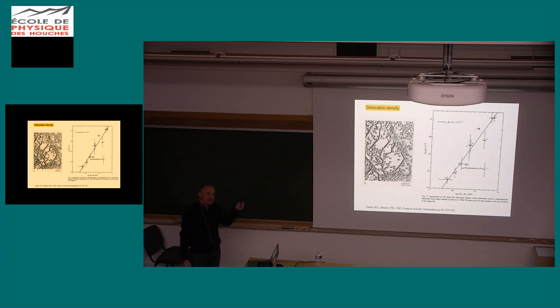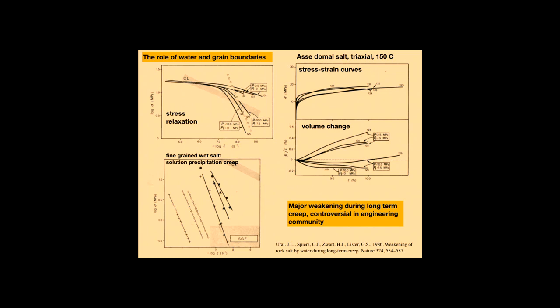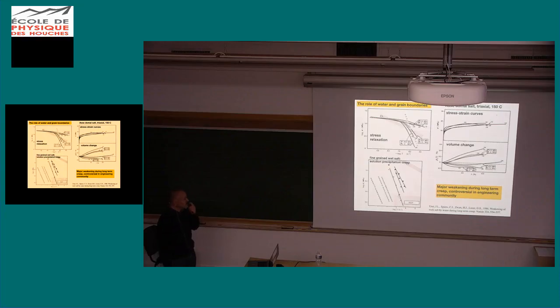So the point I'm trying to make here is that this was fantastic work, and they really tried to do the microstructures, but they didn't really have the tool to look at the grain boundaries. There was just no observational technique to do that. And when I started my PhD and we started working with Chris Spiers, we also took the domal salt. This is now from Germany because that's a bit closer. And here are a set of stress-strain curves, very, very similar to everything that has been measured before, at 150 degrees, and I think 10 to the minus 5 strain rate, but at two different confining pressures.